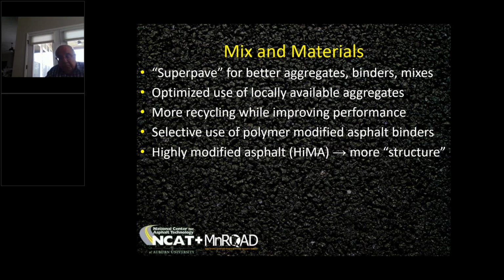And even highly polymer modified binder, commonly referred to as HIMA, that is an important part of the selective use of polymer, because with HIMA binders, you can get the performance of additional structure without the additional structure. So you can make a thinner pavement behave and perform like a thicker pavement, and that's important when you've got curb and gutter restrictions or any kind of grade issues like bridges and things like that, or just structural issues where you just can't have enough pavement thickness. Well, you can essentially create thickness type performance using these HIMA binders.